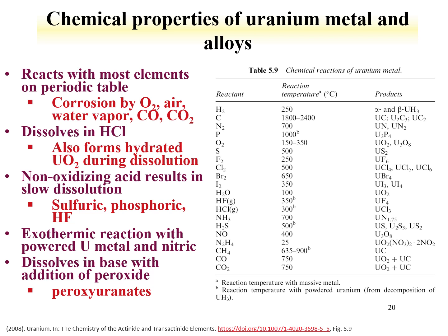The chemical properties of uranium metal and its alloys are listed here. Uranium metal reacts with, you can form alloys or intermetallics with a lot of the elements on the periodic table. The metal itself can be corroded by air, water, even under elevated temperature with carbon monoxide. This often means that if you store uranium metal, you store it under oil, so it prevents air interactions.